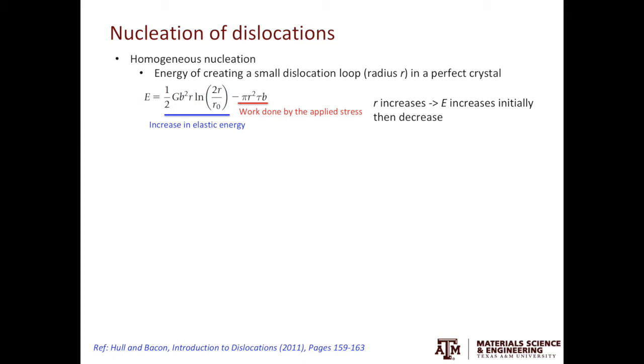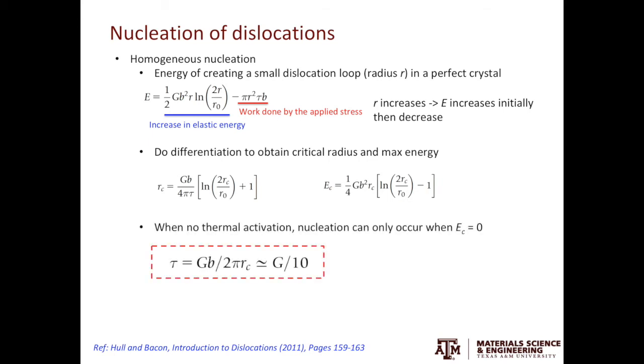If we plot E as a function of R, you will see as R increases, E the energy increases initially, then decreases. If we do differentiation of the above equation, then we can obtain the critical radius of the dislocation loop as well as the maximum energy. Assuming we have no thermal energy involved, then EC can be set as zero. We can estimate the shear stress required to nucleate a dislocation.